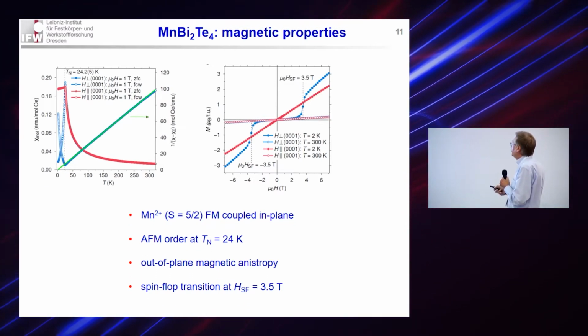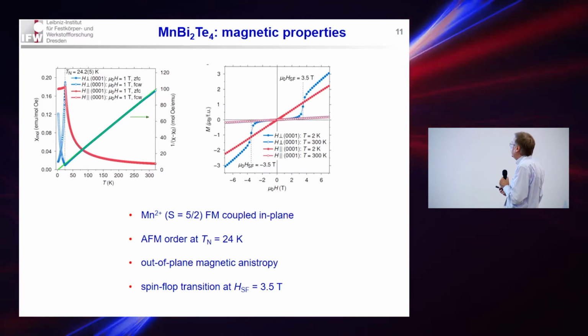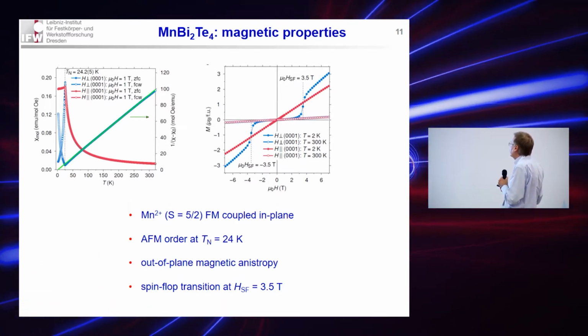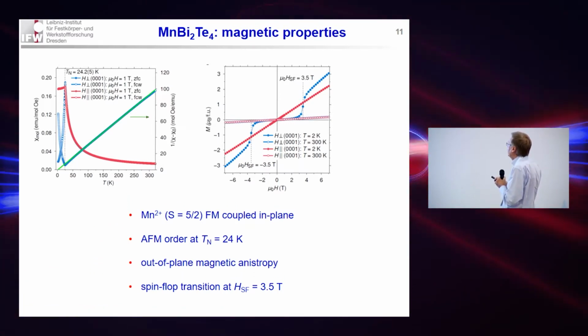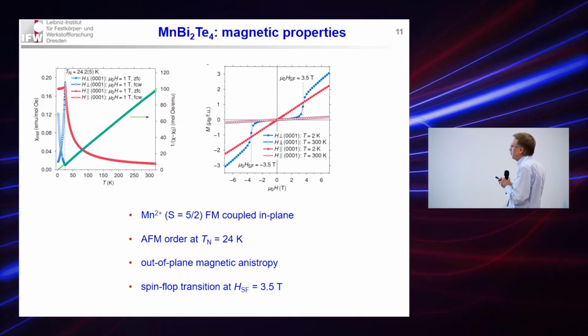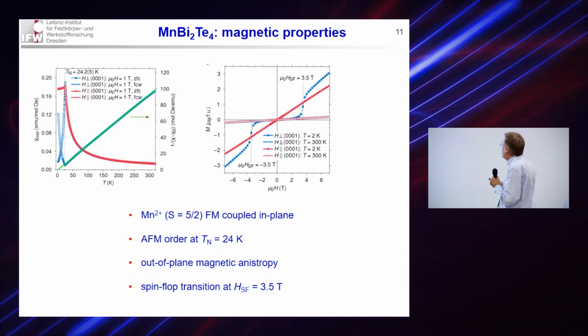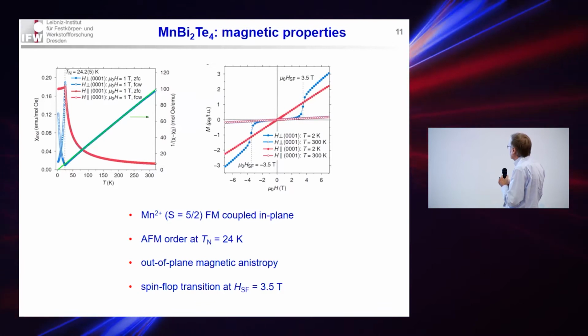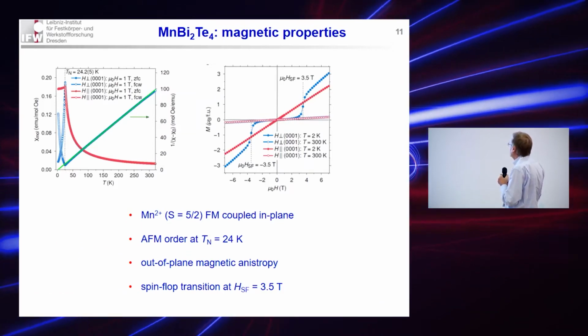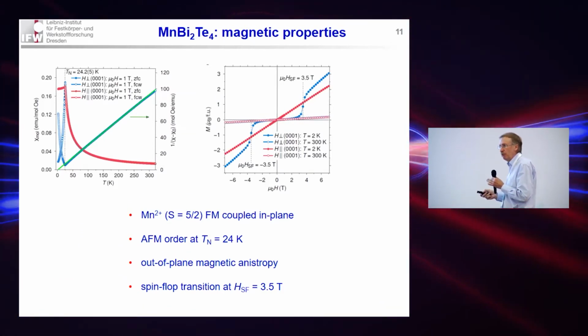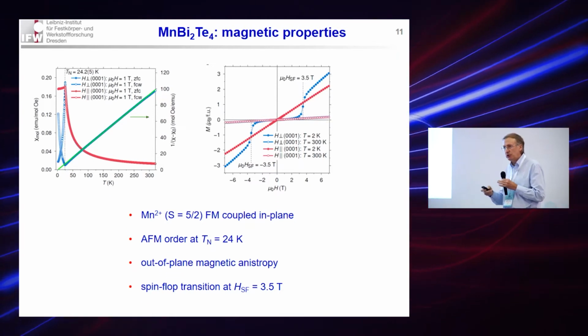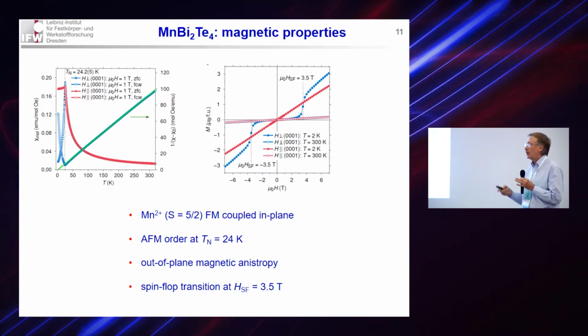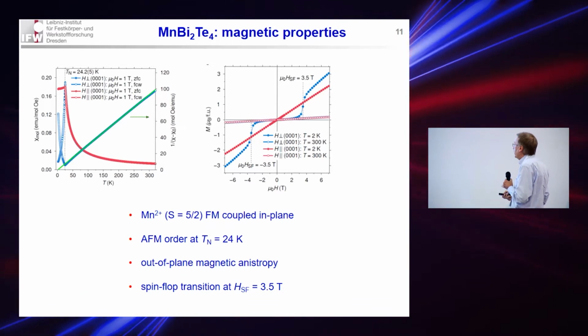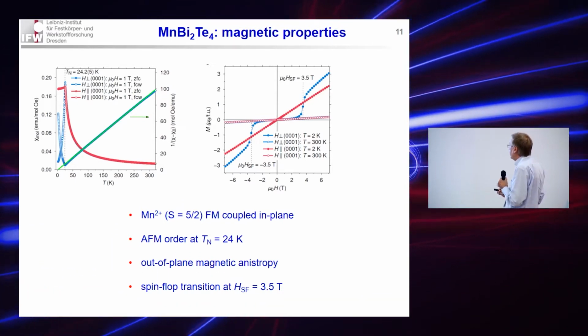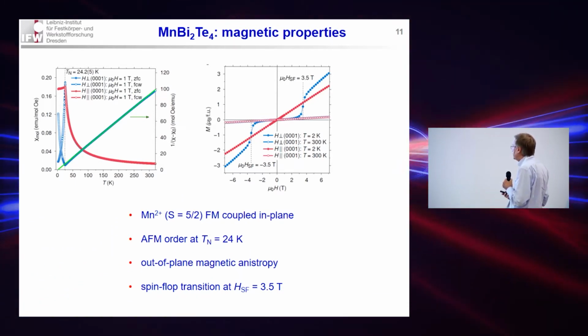Now if one measures the magnetization as a function of field in the magnetically ordered state, one sees that the magnetization is very small at small fields because it's a collinear antiferromagnet, but it has a step-like increase at a certain field, which is called the spin flop field, the field at which these two sublattices flop, and now the magnetization of the sample is increased.